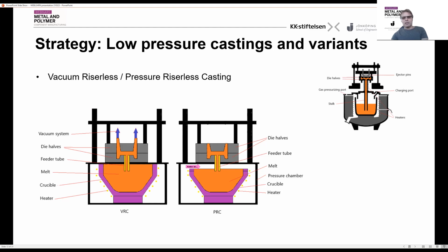The difference is that in the low pressure die casting system, the melt level is varying, but it does not do that in these systems. And that means that the variation from fill height is eliminated. So that means that you have the same pressure drop when you fill the die, and that creates a little bit more reproducibility. But again, keeping the level constant and having a way of transporting the melt in is a little bit more complicated here. So we can take the next.